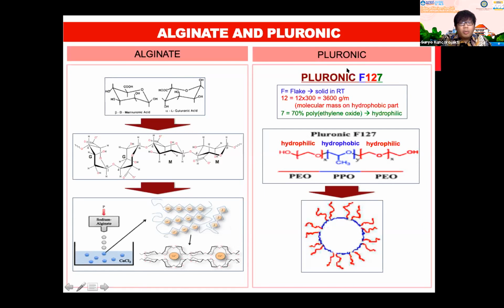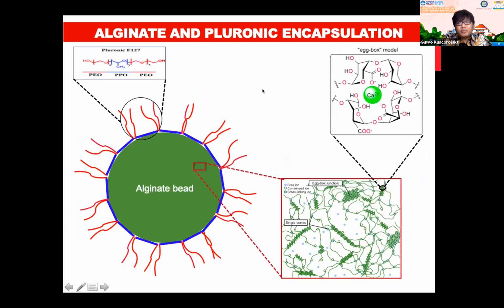While the pluronic is a three-block copolymer that consists of three parts, one hydrophobic site and two hydrophilic sites. And the pluronic is thermosensitive. In cold conditions, they will be in the liquid phase, but at room temperature, they will be in the solid phase. Then how about the encapsulation platform that we developed? It looks like this, with the alginate bead in the center, and the pluronic as a double coating binds to the surface of the alginate bead, and the hydrophobic sites bind to the surface of the alginate itself by covalent and also hydrophobic bonds.